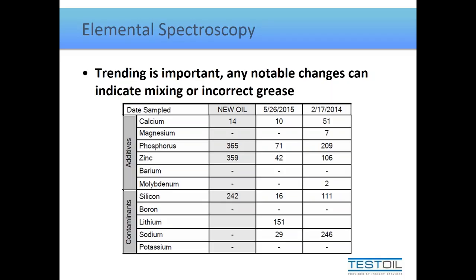Water contamination doesn't bode well for most greases — it can outright displace the grease, and since water is a poor lubricant, you'll get a sudden increase in wear. It can also cause corrosion or pitting of parts. You might not always see wear increases immediately; it's very possible to see water contamination long in advance of any wear or corrosion. When corrosion or wear does appear, it may not show up in elemental spectroscopy but only in analytical ferrography or ferrous wear concentration.